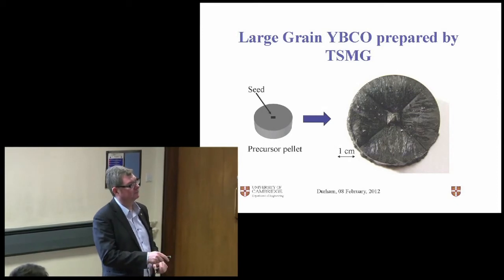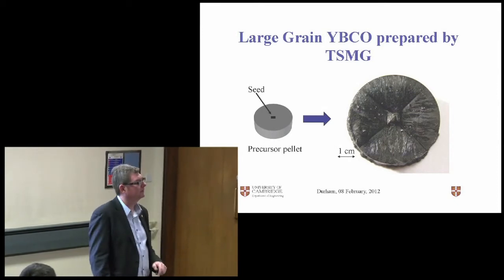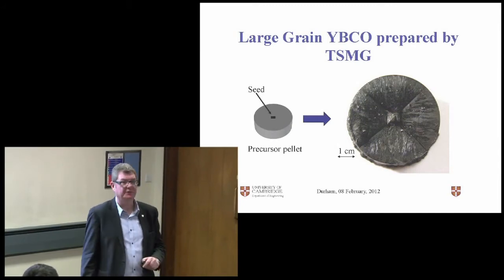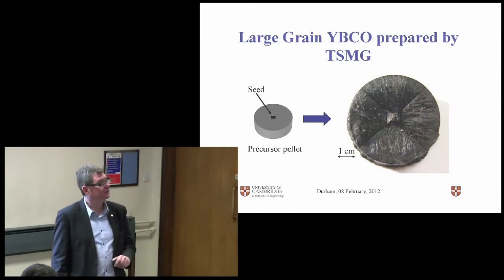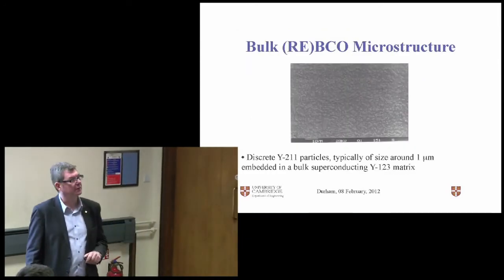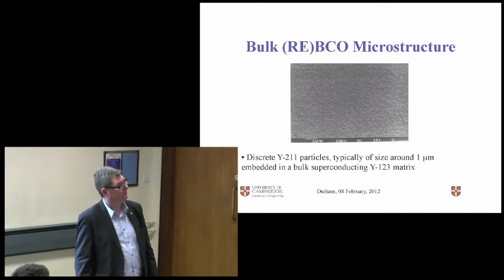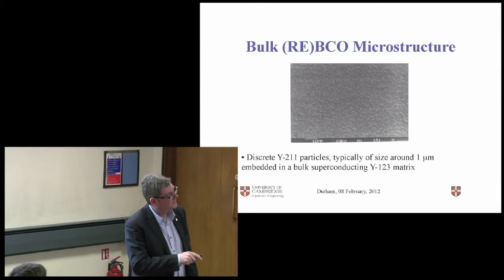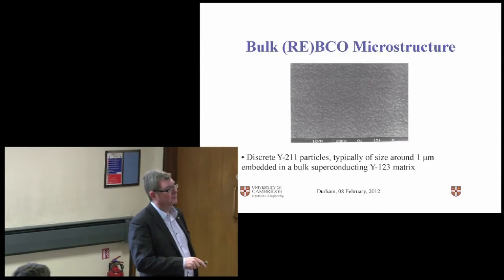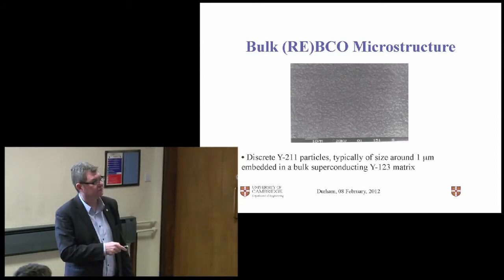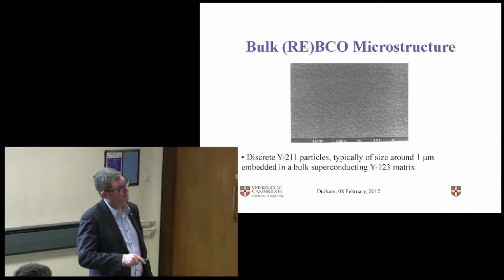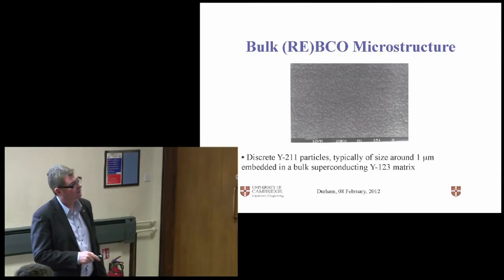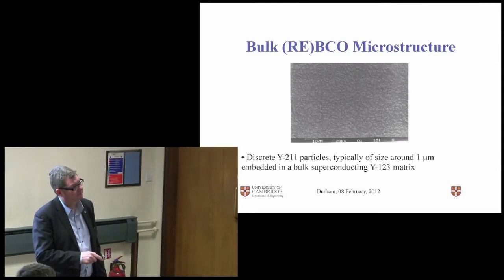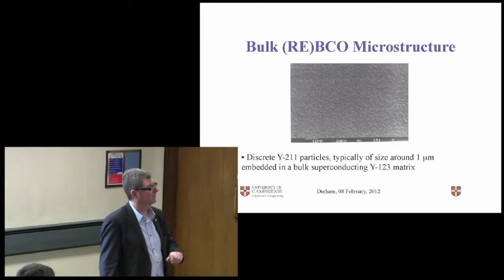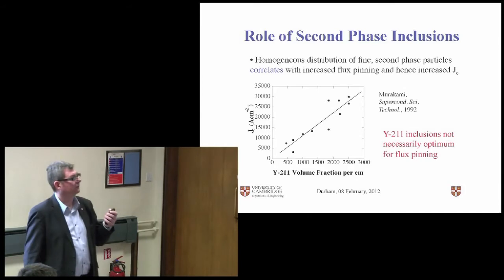If you were to make a single crystal of YBCO, I think our colleague made a single crystal 2 millimeters diameter after a 6-week growth process. So you can't make them in a single crystal form, but you can make them in melt process form. And if you look at the microstructure, you see all these 2-1-1 inclusions in there, and then there's a continuous percolation path all the way through, and we can speculate that these 2-1-1 particles might become magnetic flux pinning sites. So we could say we're killing 2 birds with 1 stone. We're growing the material, and if we can make these micron-sized 2-1-1 particles even finer, they would form effective flux pinning sites. Well, that's what we thought.